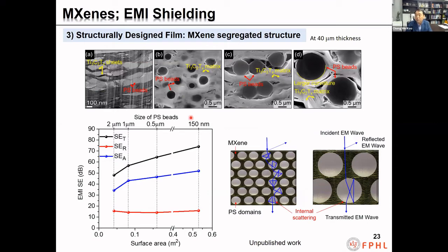The internal scattering effect is also observed in the segregated structure. We prepared MXene polystyrene segregated composite composed of MXene flakes and polystyrene beads. SET, SER, and SEA increase with the increase in the surface area of insulating polymeric domain in the composite. This is the first direct evidence that shielding performance is quantitatively proportional to the area of multiple interface in the segregated structure. This result also agrees well with the theoretical calculations.